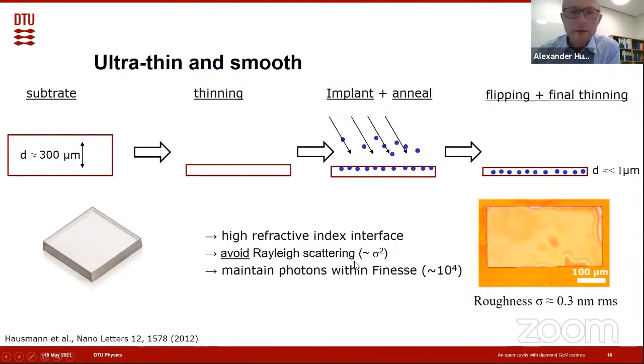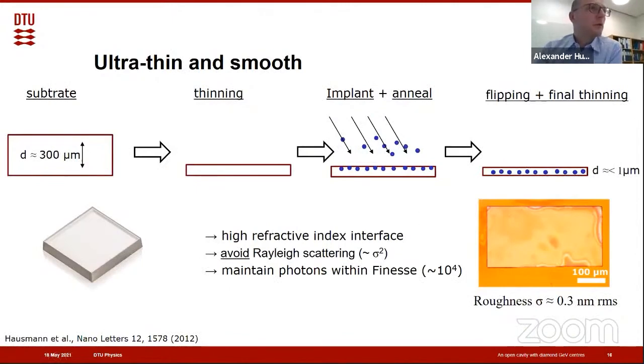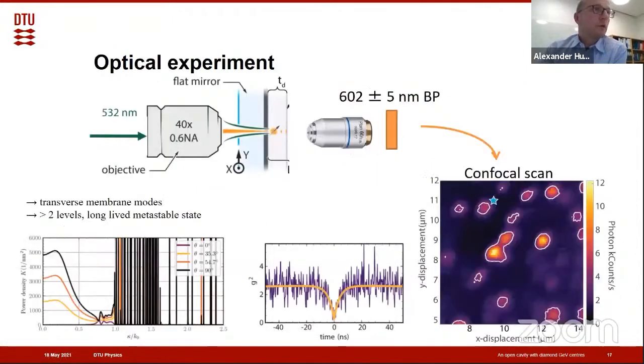What we need to keep in mind is that we have a target finesse of just about 10 to the power of 4. That means any reflections or scattering from the surface due to Rayleigh scattering, in the range of one event in 10 to the power of 4, would actually spoil the cavity and make the system not usable. So a typical experiment now looks like this: we load this diamond crystal